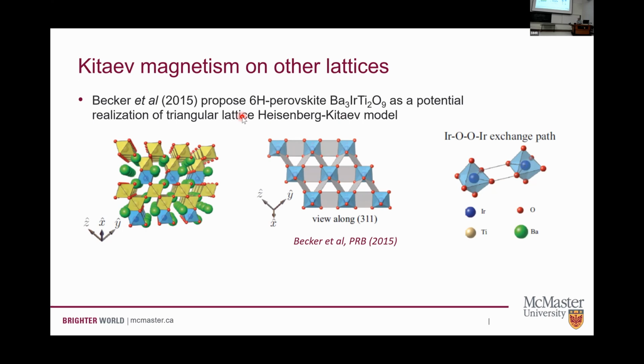And so the argument here is you still have iridium O6 octahedra, and now they're separated by some greater distance. And so you can still imagine the same exchange path argument between this iridium and this iridium. You can get an interaction along this path or along this path that can destructively interfere. But when you space out these iridiums more, you potentially weaken the normal Heisenberg interactions that would go along this exchange path from iridium to oxygen to iridium. And you also cut down on any direct overlap between the iridium wave functions. So in theory, this could give you a case where those Heisenberg terms are weaker, the gamma term is weaker, and maybe this gives you a chance to see Kitaev interactions in a different geometry.